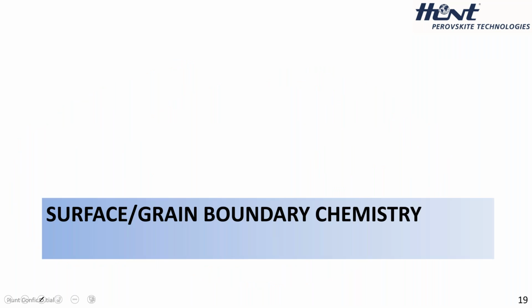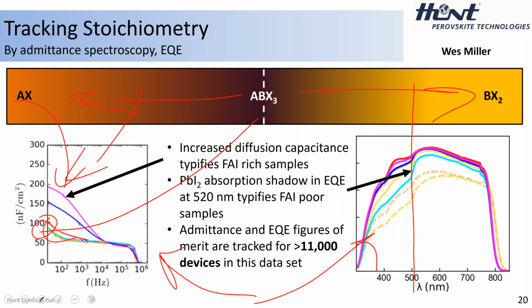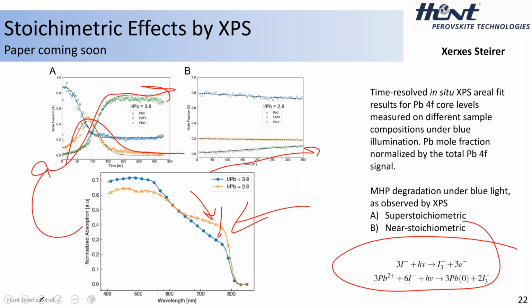And the evidence, again, here is through XPS. We can see that if you have super stoichiometric, it decomposes quickly. Just remember this, we're only measuring down about 10 nanometers into the film, versus if we have stoichiometric, the film does not decompose. So that's what I consider the direct evidence at the moment. We're working on DFT calculations to further support this.